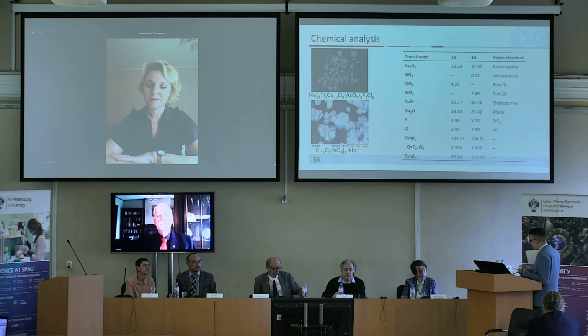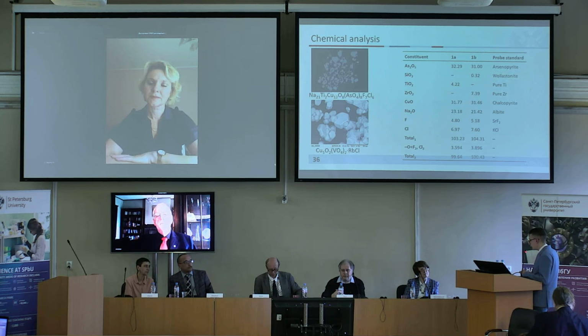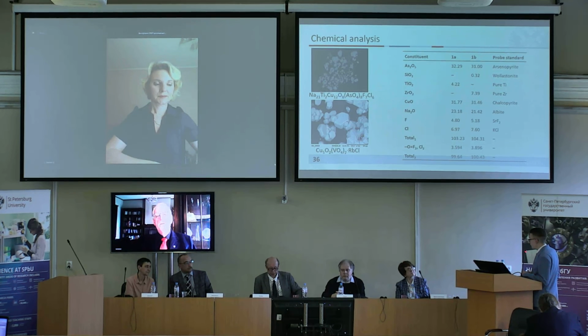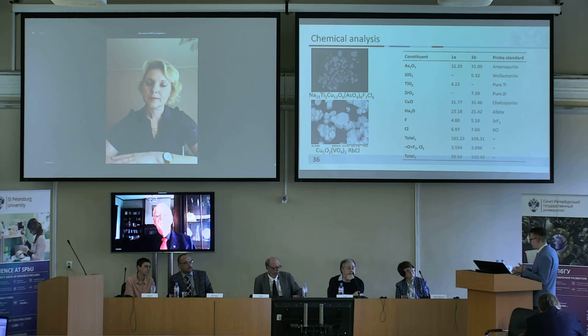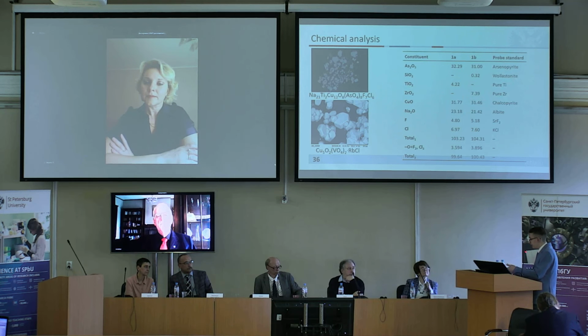And so first of all, we have to say that all the compounds with H2O and hydroxyl were obtained accidentally. These were all side products, and they all crystallize in selenite systems, which is very hygroscopic. So it absorbs water. When you start heating it, the selenite starts to evaporate. So it was hard to take water out of this synthesis. So obtaining these substances as pure monophase samples, I failed to do this.